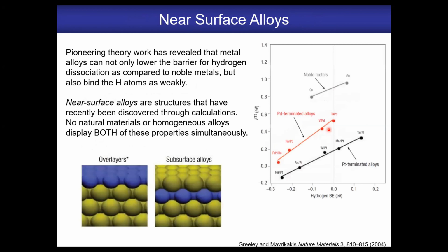So one very nice example from theory, from Manos Mavrikakis's group from over 15 years ago, of potential for escaping these linear scaling relations for the pure metals is for hydrogen dissociation on what are called near surface alloys. This is where you have a single layer of one metal on top of the bulk of another, or sandwiched between the top layer and the bulk of another metal in this sandwich structure here.